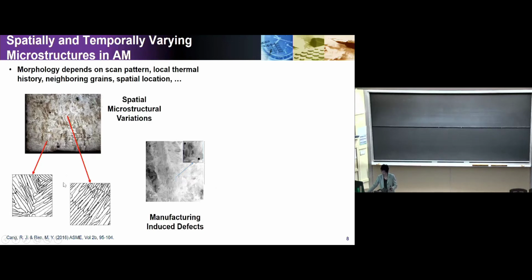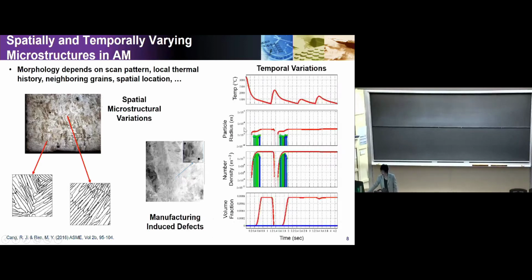Okay, so there's microstructure, which relates to your material, so that's related to material design decisions. But there are also defects that you have to take into account when you think about the property. In general, this shows it's also a function of time. You can see that the volume fraction at each different location at a different time also has variation. So different quantities show temporal variation as well as spatial variation. So it's high dimensional because of this reason.